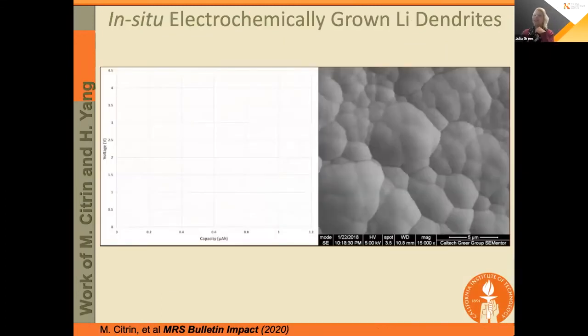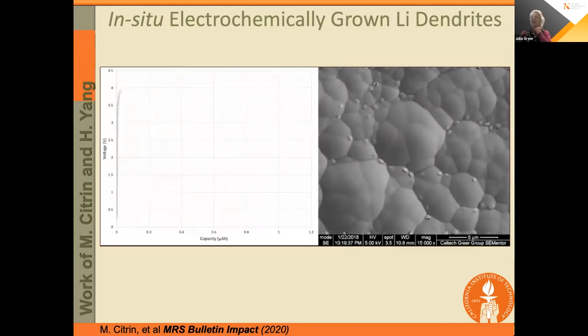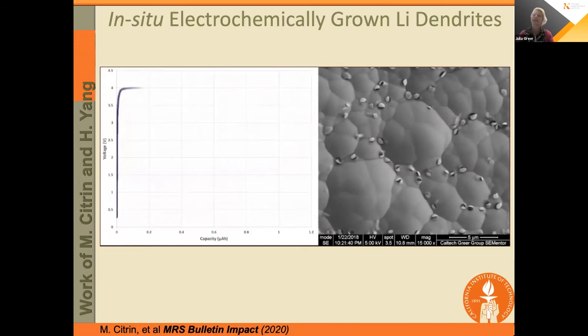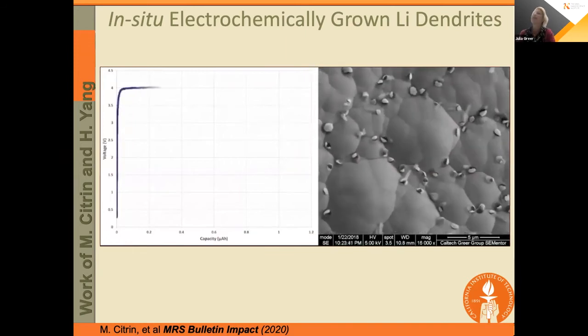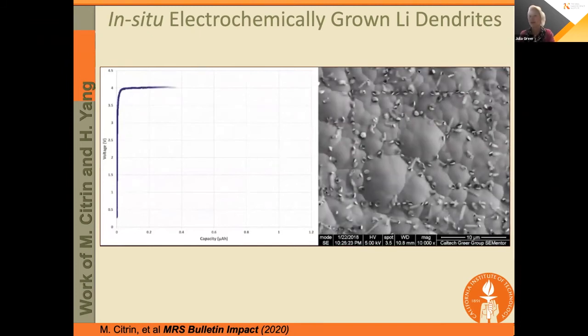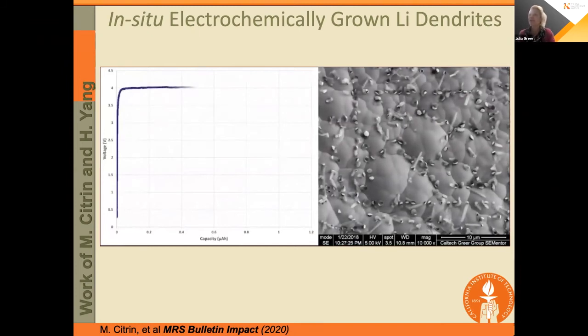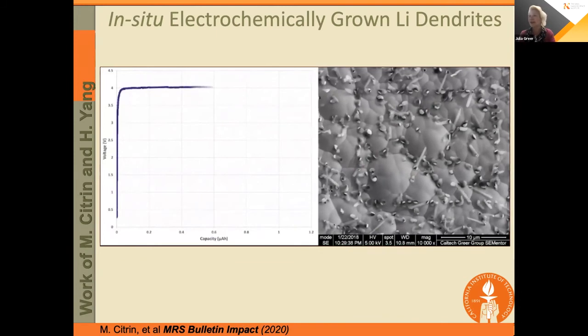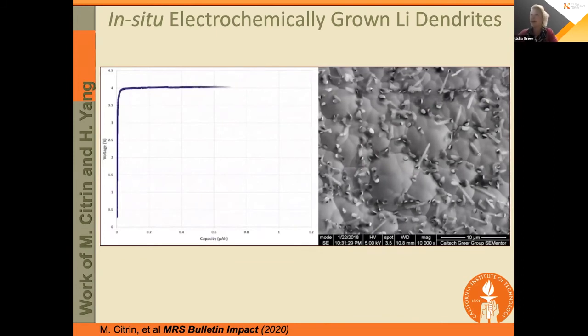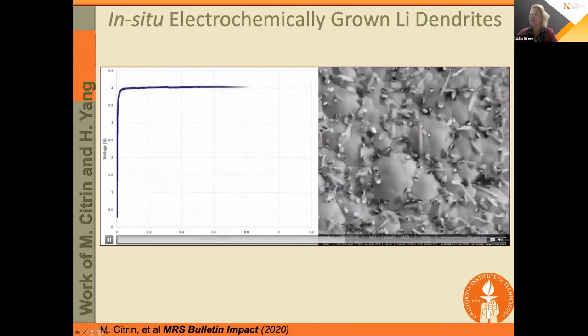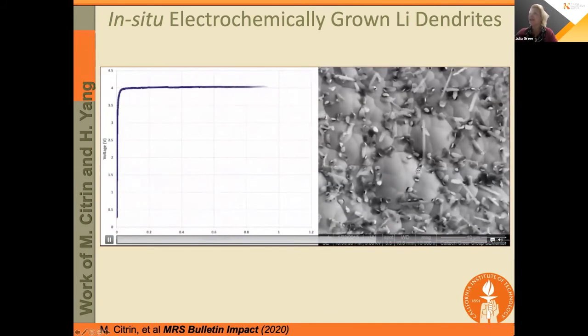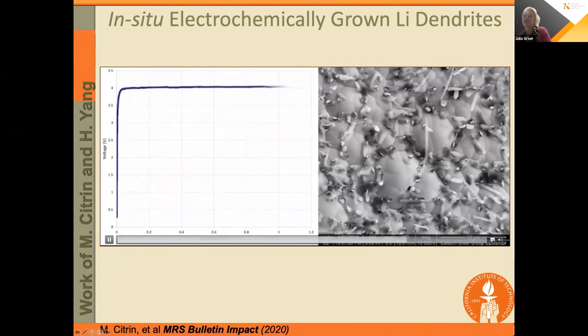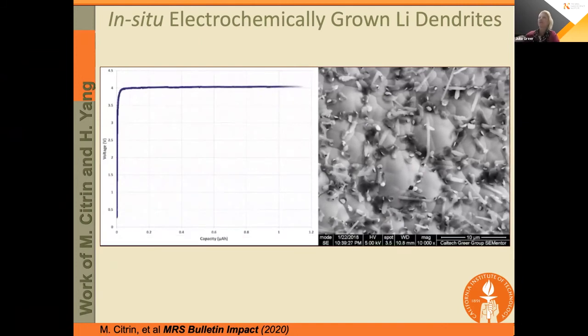Now, switching gears just a little bit, and I mentioned that everything at the nanoscale was still very much governed by defects. Well, just to tie it together also to Lars's talk, I'd like to show you one of the biggest defects or pests, and that is the lithium dendrite formation during electrochemical cycling of a battery. So this is some of our more recent work. So this is a solid state thin film battery, which is originally lithium metal free. And what you can see is the formation of these notorious lithium dendrites, which effectively break through and tear through the copper current collector and grow out of the electrolyte.